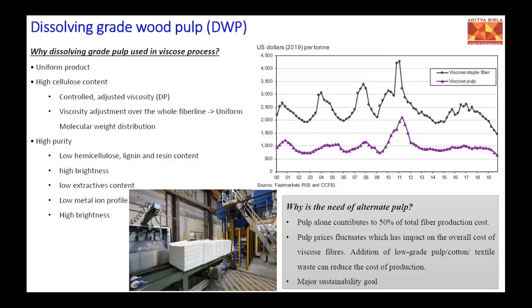These pulps also come from natural material, but they are processed in such a way that uniformity is maintained, because viscose cannot tolerate very high differences in properties when we change from bale to bale. It has high cellulose content. Just now I said more than 90%; 92-94% alpha cellulose content should be there in the pulp. Then the viscosity should be controlled. It is a very important parameter, because finally I have to prepare a polymer solution. If the viscosity changes even slightly, there is a major impact on the final product, either in the processing or in the properties of the material.